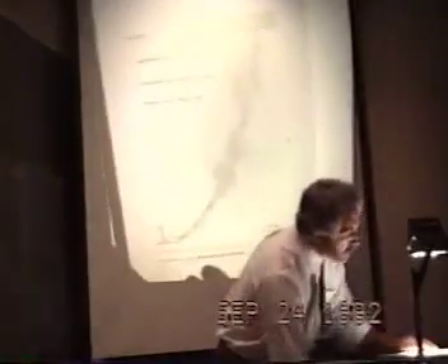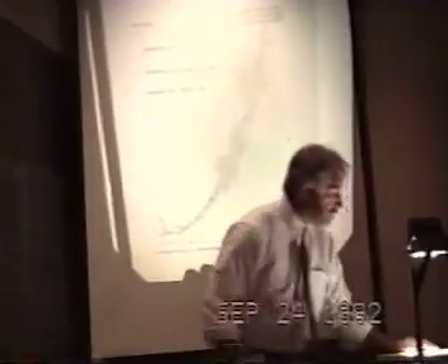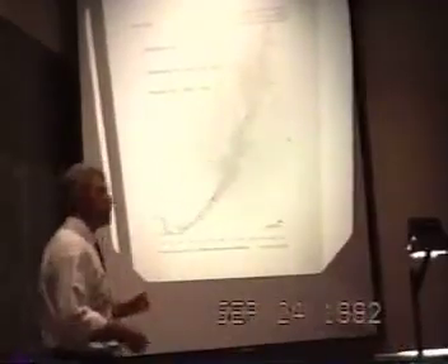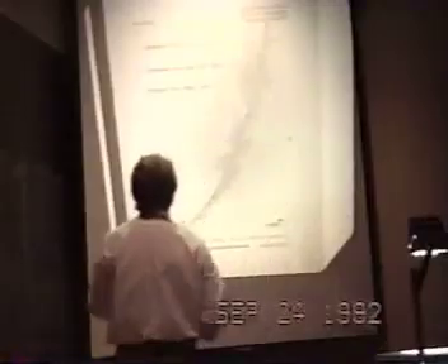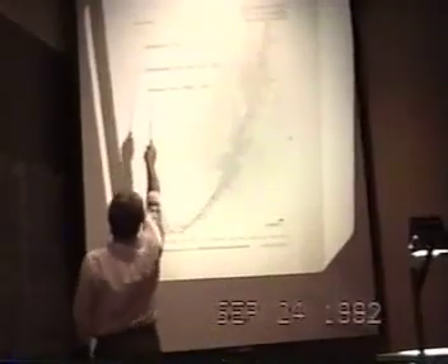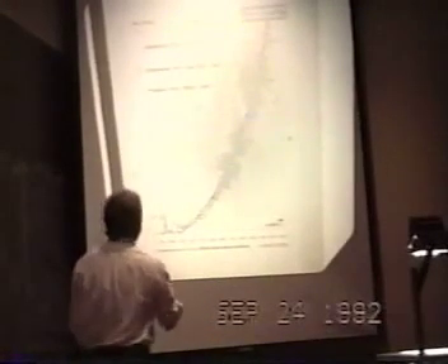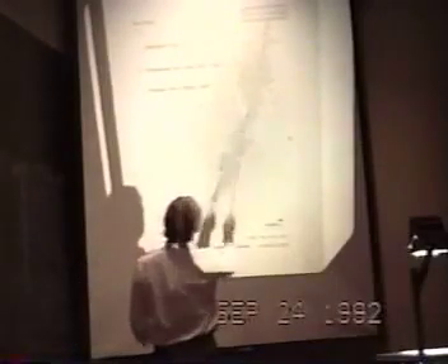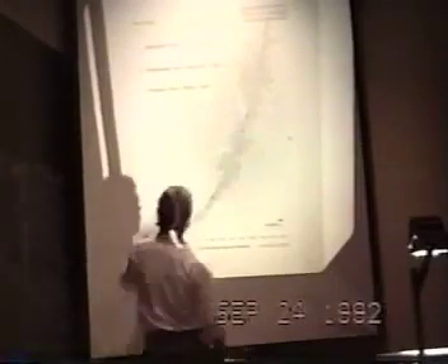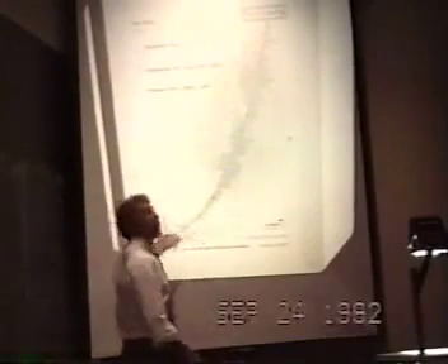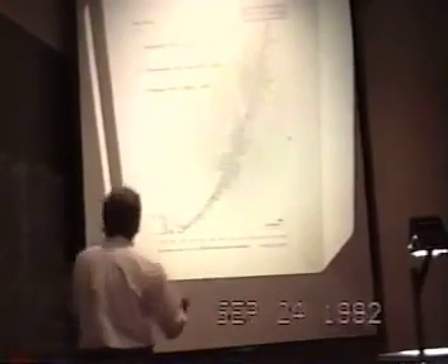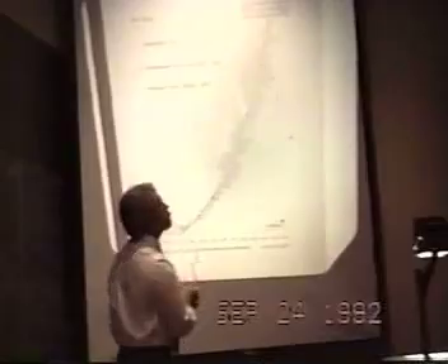Unfortunately, there's a lot more that I really need to say. One of the things which I wanted to show you is from one of the more recent cells, we were able to observe the correlation with statistical significance between the excess power observation expressed in terms of watts per cc and the loading. And I fitted three functions to this. So excess power, loading determined by the resistance ratio. I fitted three functions, and you can clearly not distinguish between them.